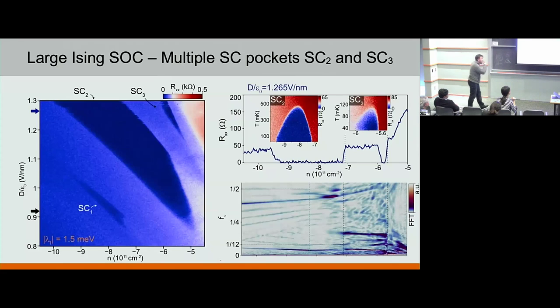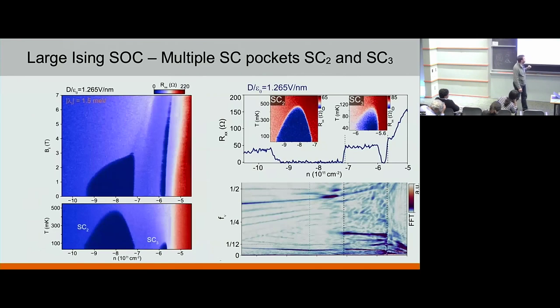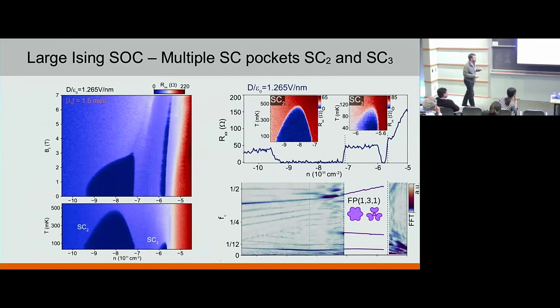Okay? So now the challenge here is that if you look at all these lines, the assignment of the Fermi pockets is not super straightforward. I'll show you the Fermiology in a moment, but as a reminder, this superconducting pocket here actually survives all the way up to 7 Tesla, while this pocket here, which is very symmetric in critical temperature, becomes very asymmetric with the in-plane magnetic field.